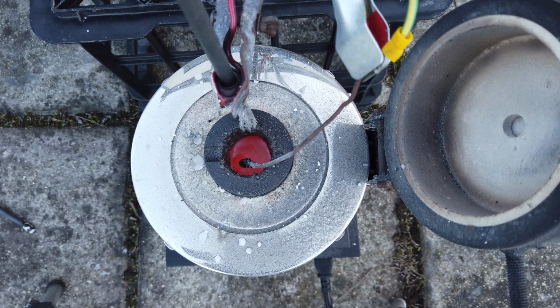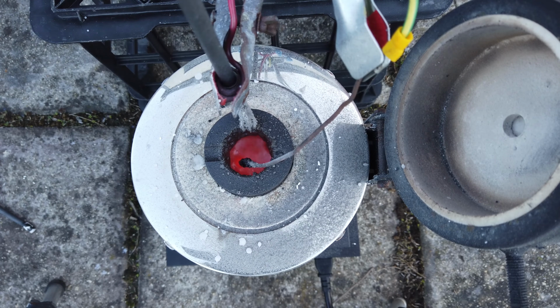So what I expect is happening is possibly our calcium chloride in the initial bottle that we got it from maybe had some calcium hydroxide or calcium oxide in there, which, if they were added to the calcium chloride mixture, would result in oxygen being generated on the anode instead of chlorine. And I think that's exactly what we're observing here.